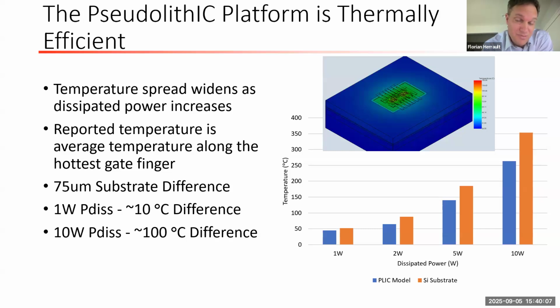Why? Because we still rely on the performance of GaN on silicon carbide. Even though we do this in a hybrid solution, all of the heat flows straight down in this high thermal conductivity silicon carbide and into the package. The fact that we have a smaller chiplet or that we have a dielectric embedding around the chiplet does not deteriorate the performance of the native GaN on silicon carbide. And that's really a powerful statement and a testament to the high performance GaN on silicon carbide technologies that have been developed by several of those US leading edge foundries.